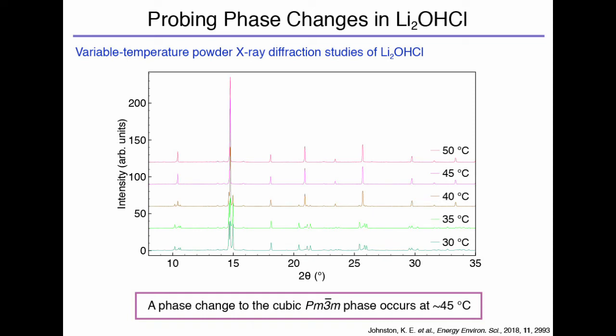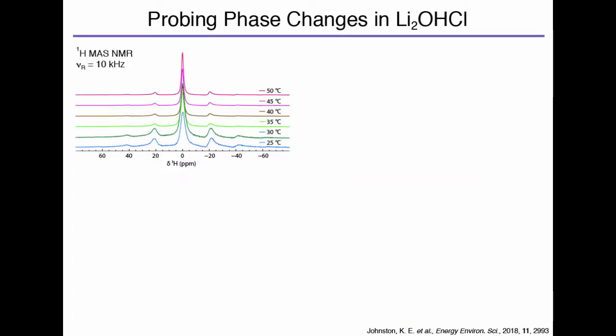So the first thing we tried to do was actually take our sample of Li2OHCl and heat it up to see if we could observe this known phase transition. And we did this initially using X-ray diffraction, so just looking at the long-range structure of the material, does it change as a function of temperature? And the answer was yes, you see a very distinct change between 40, 45, and 50 degrees C, i.e. you see lots of peaks disappear, and you get very much fewer peaks at the higher temperatures. So we could clearly observe this phase transition that was taking place.